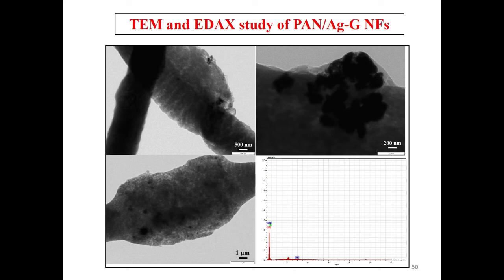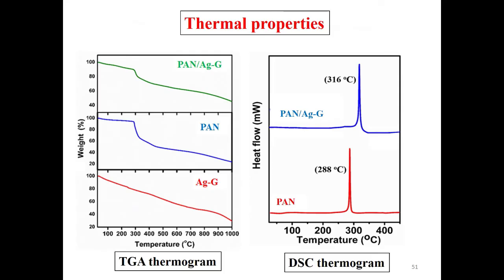This is your TEM and EDX, showing the presence of these particular elements in the fiber. Very high porosity, looking very transparent. Because of the high porosity, this material is going to be very effective in various applications. Thermal stability is found to be very impressive as compared to the other material.